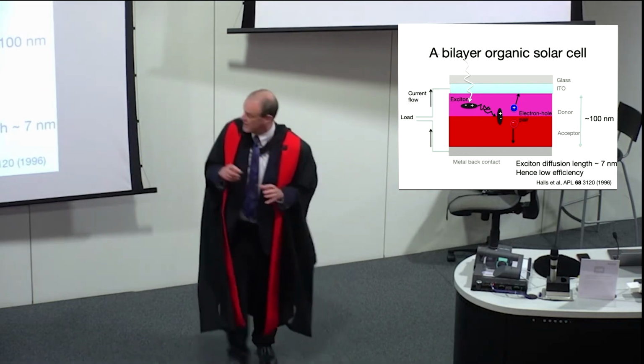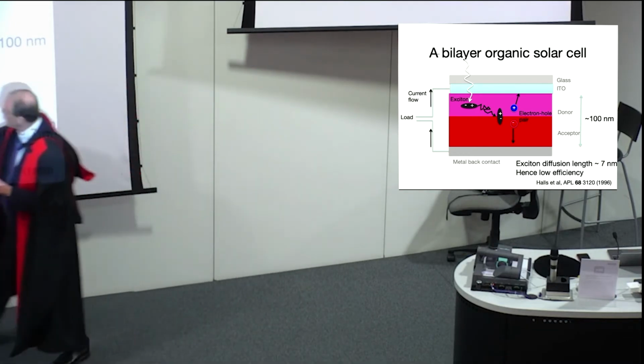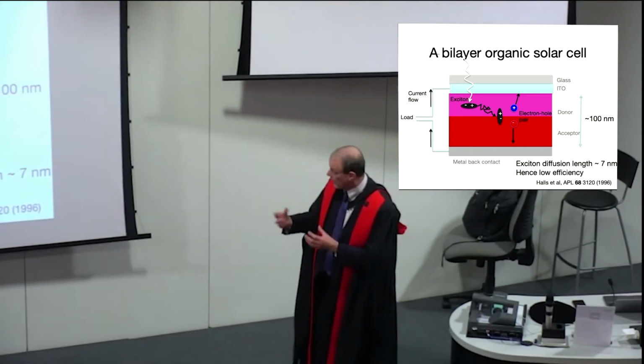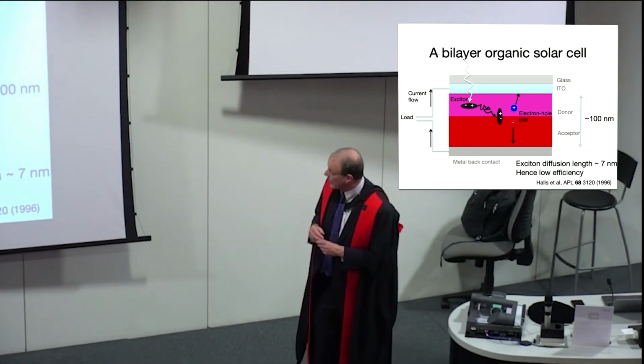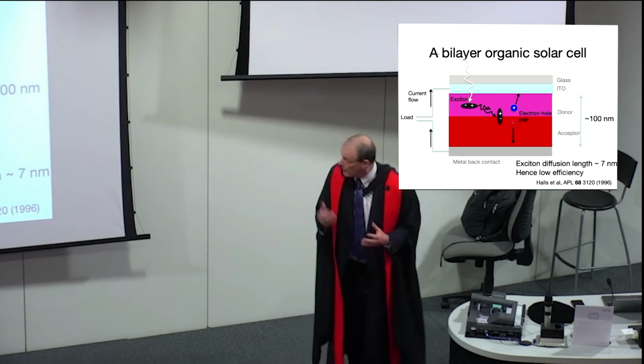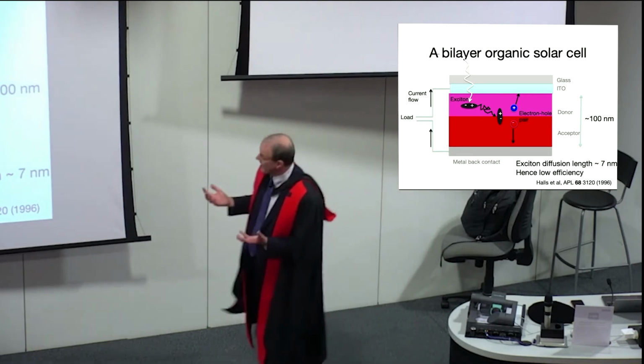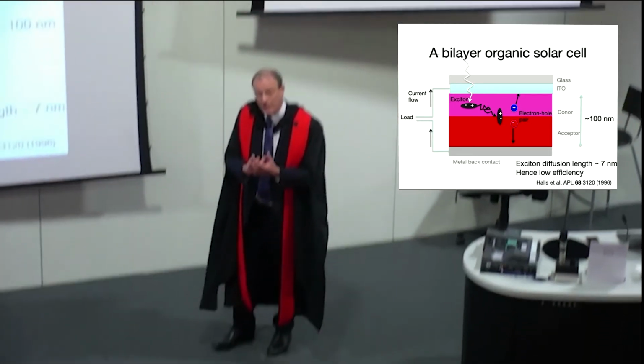And so what this means is this only works if you've got an interface, so that the exciton goes to the interface and then it gets split, because the two polymers have got different band gaps, essentially. But the problem is the excitons can only diffuse about 7 nanometers before they recombine.